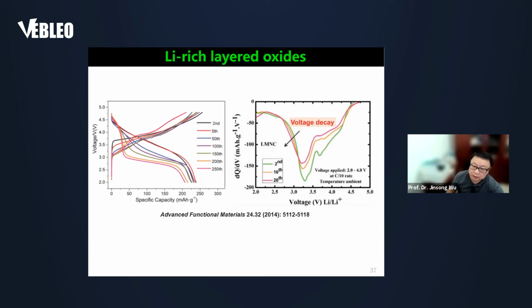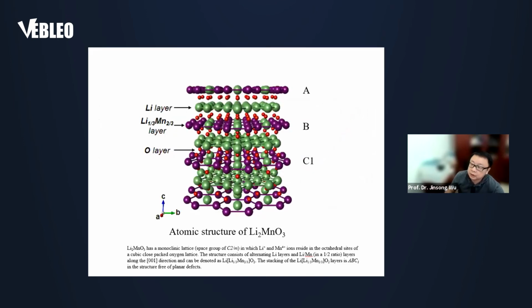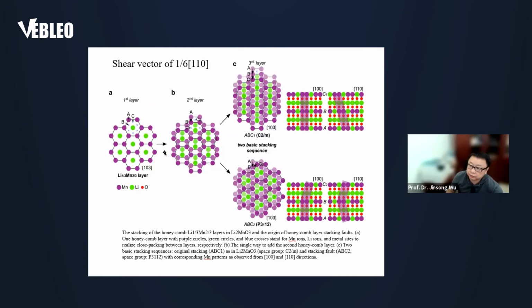And we want to find out why, and see what's going on during the voltage decay. When we look at the structure of LMO, looking at the cation layers, we have a pure lithium layer, then a lithium manganese layer, then a pure lithium layer, a lithium manganese layer, a lithium layer, a lithium manganese layer. Of course, among them there are oxygen layers. And if we look at those layers, one layer along the same direction is related to the next by a shear vector of 1/6 <110>, which means if we shear this layer by this vector, we get to the other layer.